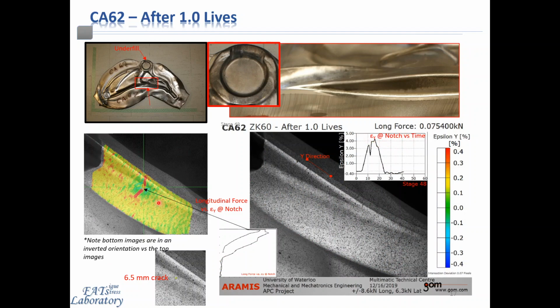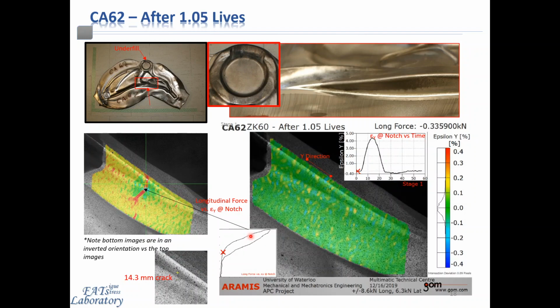So this red line on the image here is what's indicating the crack, surrounded by a field of green here, and that is complementary negative strain to satisfy continuity at the surface. So we are fairly certain that this isn't just some measurement anomaly. We're actually observing a crack here, as we have the complementary compressive fields surrounding this tensile saturation of strain here. And we can see much more area being enveloped in the hysteresis loop only in the tensile region, which is what we would expect once the material has cracked.